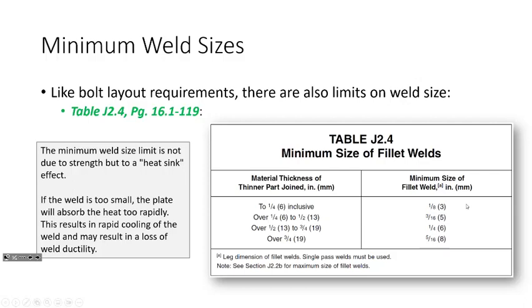But if I have this 4 inch thick plate and only a 1/4 inch weld, what I'm proposing is that that super thick plate is acting like a heat sink, right? It's absorbing all of that energy, and so the weld you deposit won't behave the way that you want it to, because all that energy you deposit for that tiny weld got absorbed by the plate. In other words, you get a heat sink effect, okay? I propose that if you're going to deposit a fillet weld, that fillet weld needs to have some size to it so that you don't get rapid cooling of your weld and loss of weld ductility, okay? So dependent upon the material thickness of the parts that you're joining together, you have some minimum size of a fillet weld to try and avoid that heat sink effect. Does that make sense? That is the reason for a minimum fillet weld size.